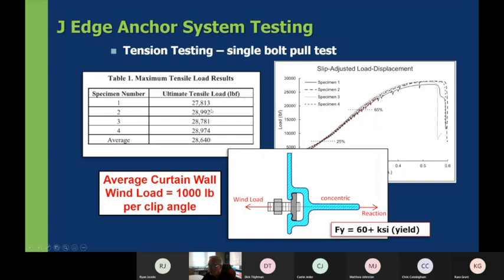For the tension only test, we were able to get up to about a mean of 28,000 pounds. And you can see that the average curtain wall load for a clip angle is typically about 1,000 pounds. And so we're well down below that load curve on the far end of that to where it's good.